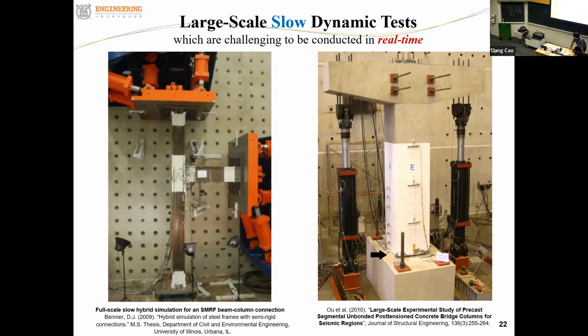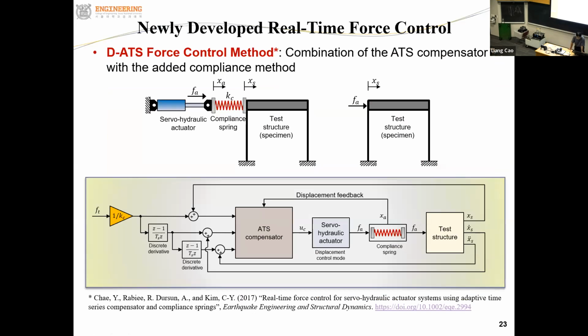So these 2 figures show some of the existing tests for the steel beam column part and the reinforced concrete bridge pier. Because the actual force control was very difficult, these existing tests were only conducted slowly to have better control of the actual force or actual displacement. So at the time, it was very difficult to have good accuracy in actual force control. So in order to resolve this kind of issue, we developed a new force control algorithm, which is called the DATS force control method. The idea here is very simple.